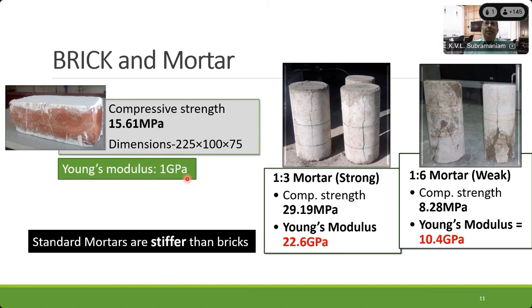And this is typical of what we are finding of bricks in India today. The bricks are strong. That is, they have a high compressive strength, but they have a very low modulus. That means they are very soft. So what is happening now is the story in India is flipped. Typically, when we talked about masonry, we would have bricks which are hard-fired clay bricks, which were very strong and very stiff because they're almost like ceramic. Or if you make masonry with stone, it is also very strong and very stiff.